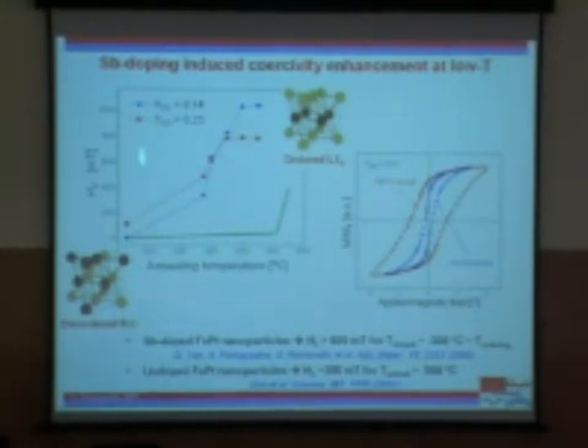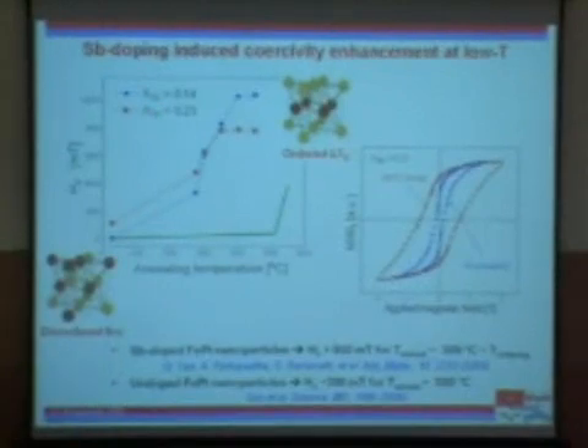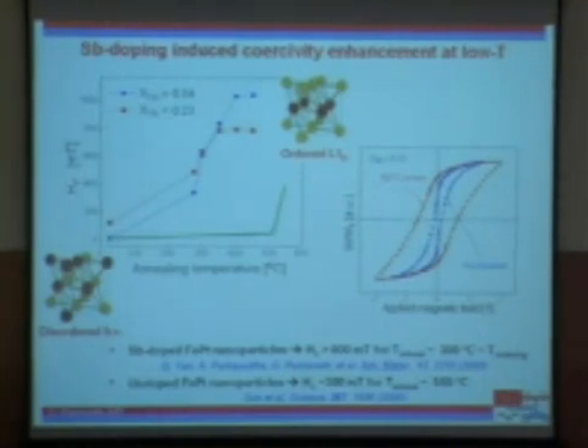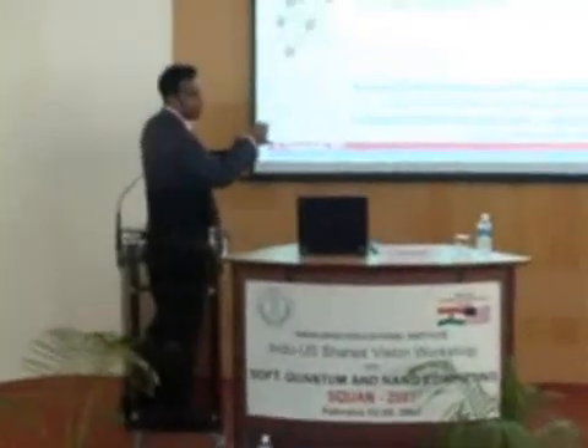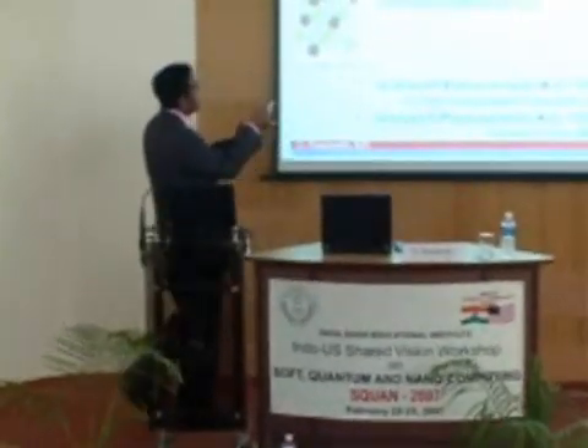Now, by adding this antimony, the idea is that antimony is a big atom, and it also doesn't like to stay in the lattice of iron and platinum, so it likes to go out. The moment you heat that a little bit, it's going to shuffle the other atoms, and hopefully that will drive it to the high coercivity phase. That is the idea, and indeed it does. As you can see, at about 250 degrees centigrade, you start to get the high coercivity values.